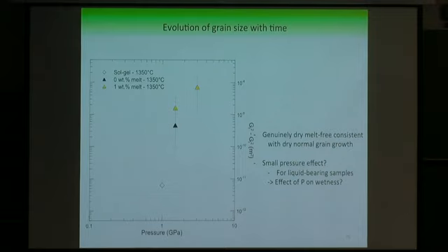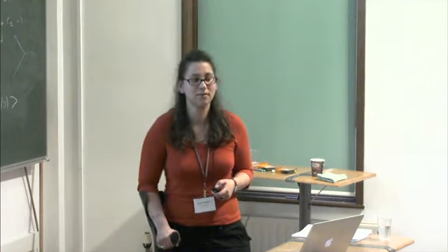So if we plot this data as a function of pressure, well, we can maybe say that for liquid-bearing sample, there is maybe a small effect on grain size, and that this effect of pressure may be an indirect consequence of its effect on wetness. So there was a study from Yoshino et al. in 2009, I think, which showed that the dihedral angle will decrease with increasing pressure. But maybe we can talk more about that, Uli.